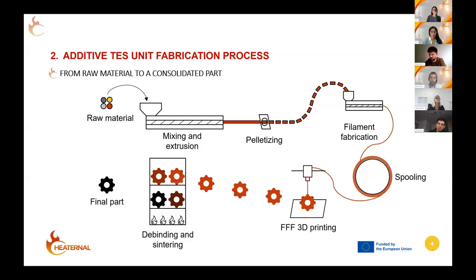Next, as it's shown in the picture, there's the fused filament fabrication process, in which the filament comes through a heated nozzle to deposit the material layer by layer. And finally, there's the debinding and sintering process. This process is a challenge, especially because we are removing the polymer first and then densifying the part to achieve the high densities needed for the best performance.